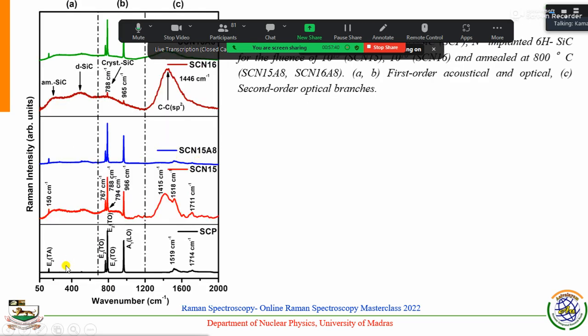Simply see, this is the Raman spectroscopy for the irradiated silicon carbide material, which means we implanted nitrogen ions. Of course, implantation breaks the bonds in the SiC and gives more homonuclear atoms, so the homonuclear vibrations give a completely broad feature. From the pristine value to the SCN 15, which means the 15 dose, if the dose increases the peaks completely disappear, which shows that the amorphous nature increases. Broadening is of course the amorphous nature. And second order Raman is also enhanced hugely compared to other things.